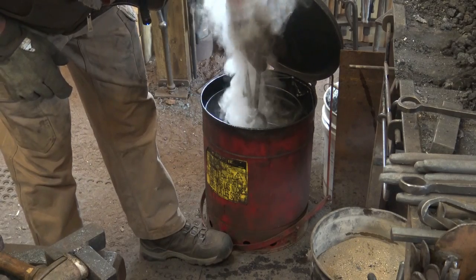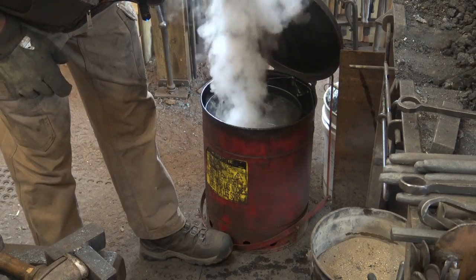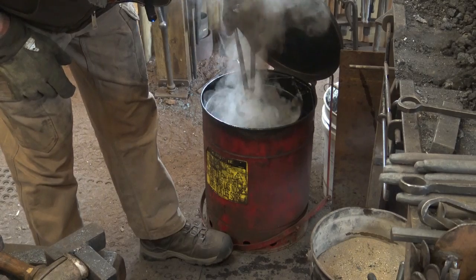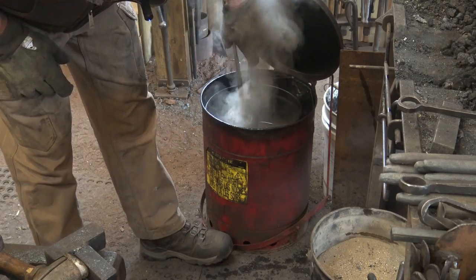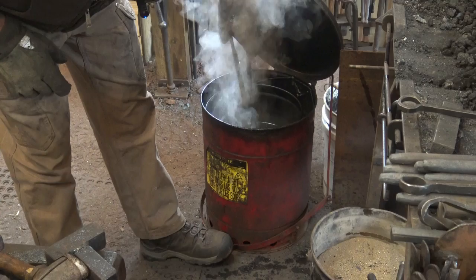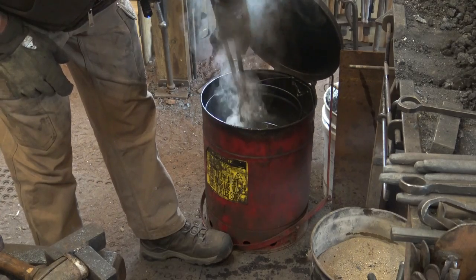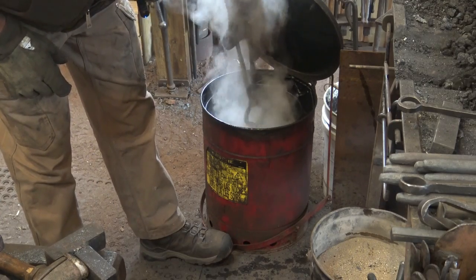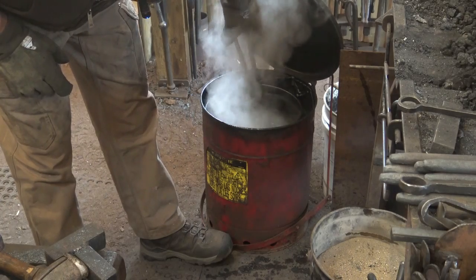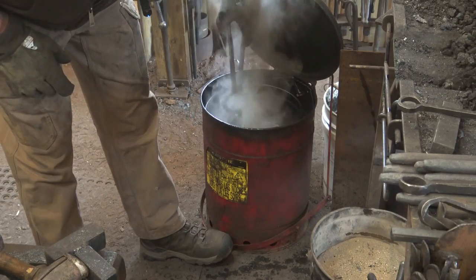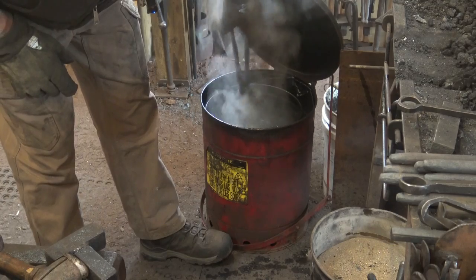But once the initial cooling is done, if I really needed to get away from the smoke, or if it flared up and started a fire, I could just set this on the bottom of the can and let the lid close, but the more you keep it moving, the more even your quench will be. So you wouldn't want to set it on the bottom initially.